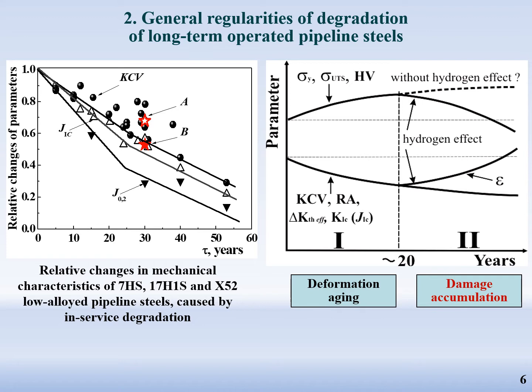It is well known that under strain aging, the strength and hardness increase, and plasticity and resistance to brittle fracture decrease. However, this tendency of mechanical properties changes could be violated if the metal undergoes in-bulk multiple damaging during operation. In such circumstances, strength and hardness of the damaged materials decrease, but elongation increases. Further operation of the degraded steel leads to an additional decrease in reduction in area and characteristics of brittle fracture resistance.